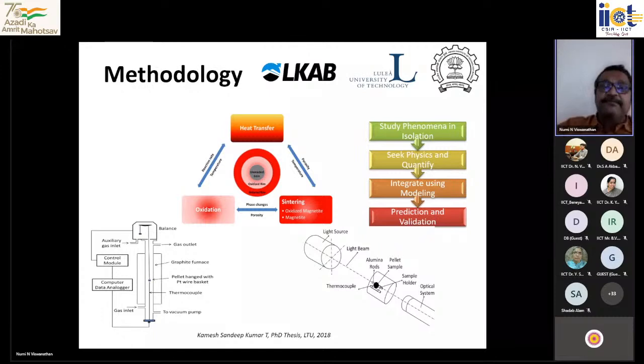And how do we do experiments? Sintering, for example: during sintering, the powder particles come closer, and because of that, the whole pellet's size decreases. This is well known to the metallurgical community. There is something called powder metallurgy, where using metallic powders one can make components. That is sintering again, and those people have conducted a lot of experiments and have good knowledge about this.